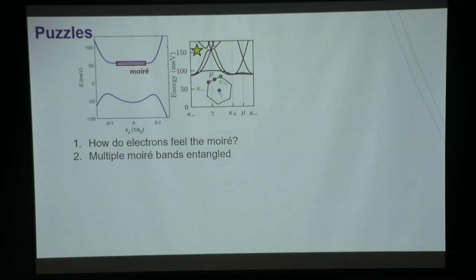Even bigger trouble is waiting for you, okay? You can fold your band structure into the Moiré mini-Brillouin zone, just like how the Kronig-Penney model works. You fold your band structure into it, and if you really do that, even with a weak Moiré potential, you don't get an isolated flat band like what you get in the Landau level case. The first flat band is overlapping with the second or even the third Moiré band in energy. And this doesn't look like a Landau level separated from other Landau levels by cyclotron energy at all.